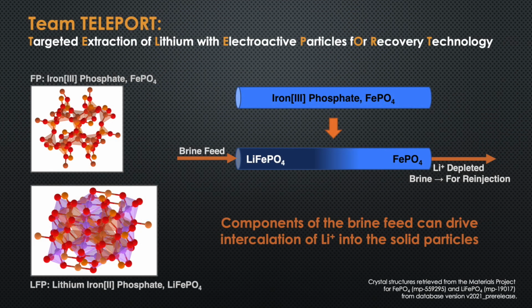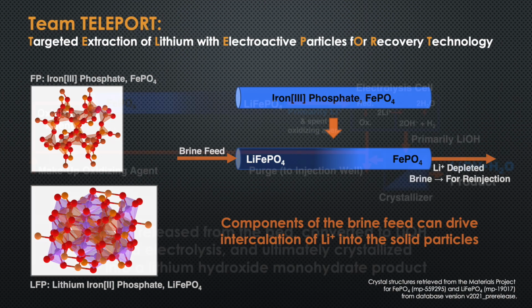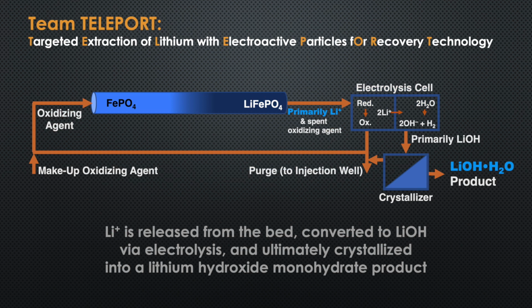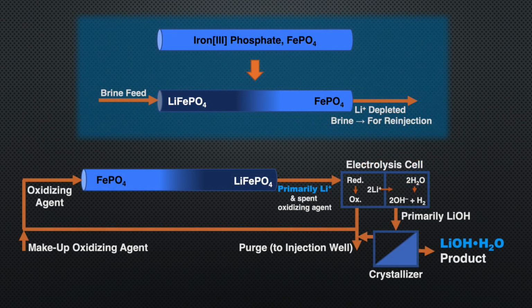The process begins with selective capture of lithium into an iron phosphate solid intercalation material, which is highly selective for lithium over other ions present in the geothermal brine. The intercalation material extracts lithium ions and decouples remaining purification processes, which include an electrolysis cell and final crystallization process to recover lithium hydroxide monohydrate product. The process starts with extraction of lithium from the brine using iron phosphate solid particles.